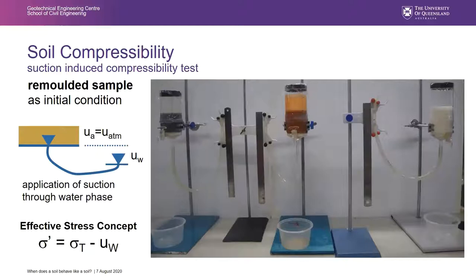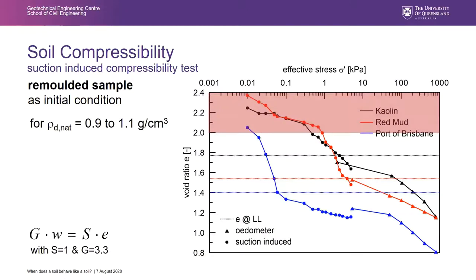What we do is to allow the sample to sediment in this cylinder. We have here a ceramic glass plate, and then we apply an increased effective stress by applying suction, by lowering this tube filled with water slowly downwards. And our sample, because the effective stress increases, starts to deform due to this effective stress. And these are the results. So basically, this is the point where we apply for the first time 0.01 kilopascal. If you recalculate that into a water table, it is just 1 millimeter of water table.